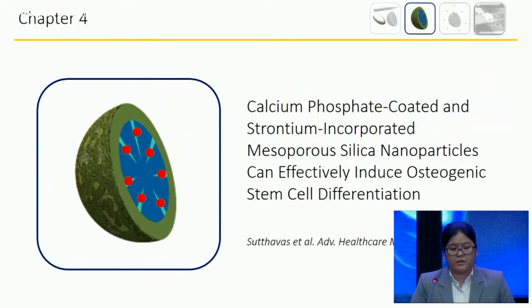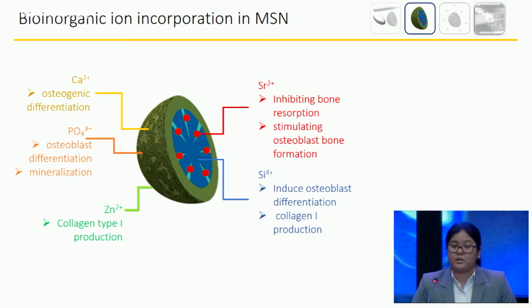Next, we explore how we could use nanoparticles to deliver several therapeutic ions to enhance the bioactivity of the material. The ion doping of ceramic nanoparticles is a popular approach in the field to improve the bioactivity of nanoparticles. However, how to best optimize them in terms of ion choice, ion composition, and ion release is not yet fully understood. The mesoporous silica nanoparticle structure can be used to incorporate multiple ions, whether in the mesopore, in the matrix, and or deposited on the surface.